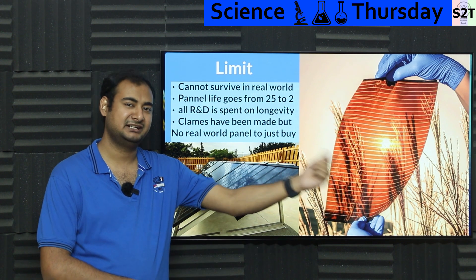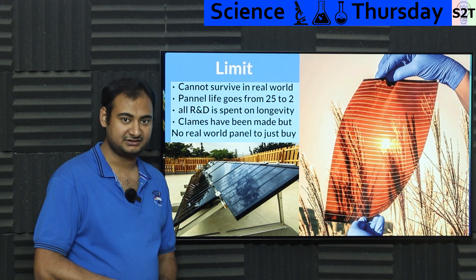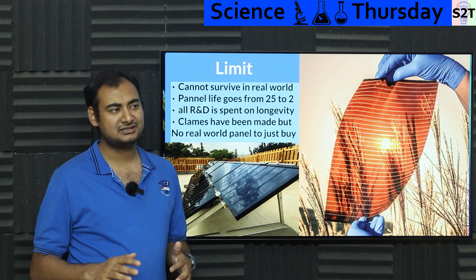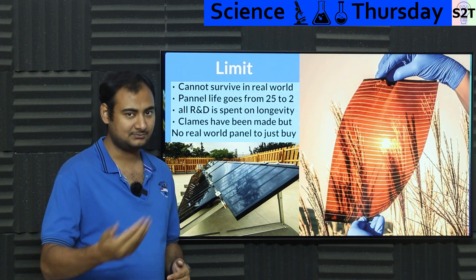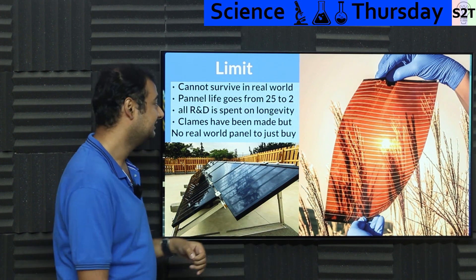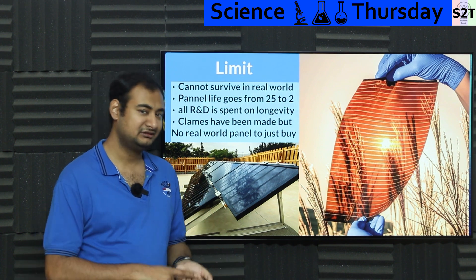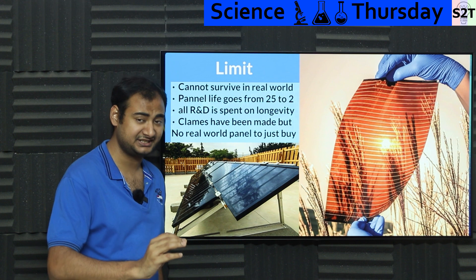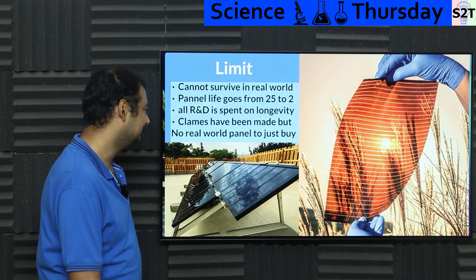The limit is this: perovskite cannot survive in the real world. It's almost like carbon nanotubes — can do everything except leave the lab. Current silicon solar panels we know will survive 25 years — we have real-world data to prove it. Perovskite? You'd be lucky to get two years. It generally disintegrates in a few months. Everybody — all companies, institutes, research labs — is working on not efficiency, not cost, but durability. Many companies in 2018–2020 hyped this, made panels, deployed them in real life, and they failed almost immediately.